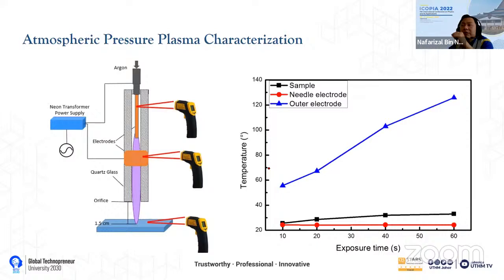In order to understand whether it is the plasma, the radical species, or the UV light or the heat from the plasma that is actually killing the bacteria, we did some simple characterization of the temperature. You can see the temperature at the electrode and the sample here is actually not high. It's less than 40 degrees Celsius.